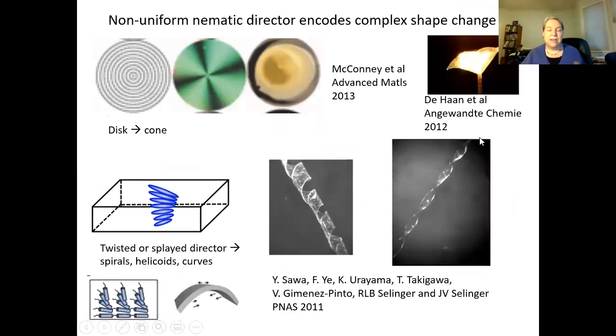Now in those cases, the nematic director was uniform, but the nematic director can also be patterned on purpose. And when you do that, the axis of mechanical actuation is not uniform in the sample, and you get some sort of complex shape change. So one of the first things that was done was to put the director field in kind of a target shape. So in this case, the nematic director is pointing around the circle. If you look with cross polarizers, you will see a +1 defect. That's the point with the four black stripes. That means that where you see black, the nematic director is parallel to either the polarizer or the analyzer.